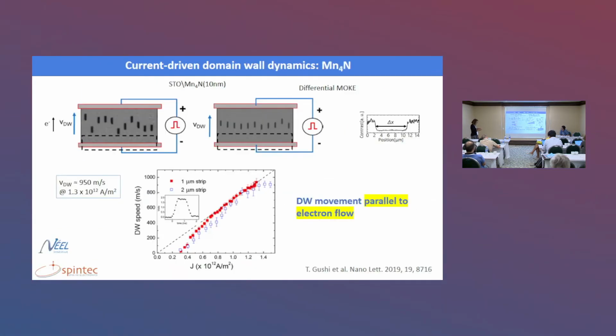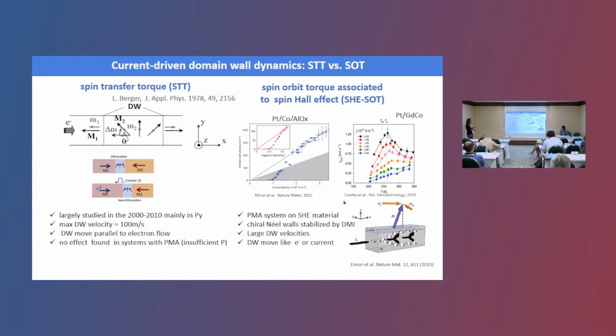As you may know, there are two phenomena that can be invoked. The first is the classical spin-transfer torque, which was studied a long time ago, mainly in the years 2000-2010, mainly on permalloy. At that time the maximum domain wall velocity was about 100 meters per second, and the domain walls move parallel to the electron flow. The current is spin polarized within the ferromagnet, and because of conservation of angular momentum, when the electron spins align parallel to the magnetization within the domain wall, a torque is exerted on the domain wall that moves it in the direction of the electron flow.